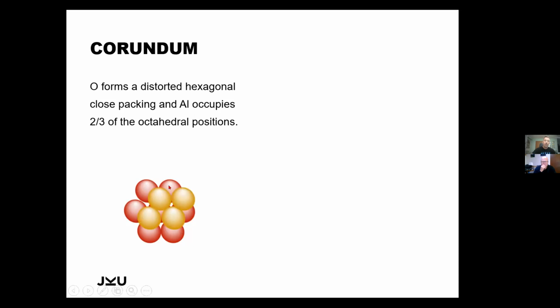And when we do this, we see that we have 3 red balls in the lower layer, and we have 3 of the golden ones, which are exactly the same oxygens on the top layer, and they form in between an octahedral void. And this octahedral void can now be filled with the cation, which is the aluminum.